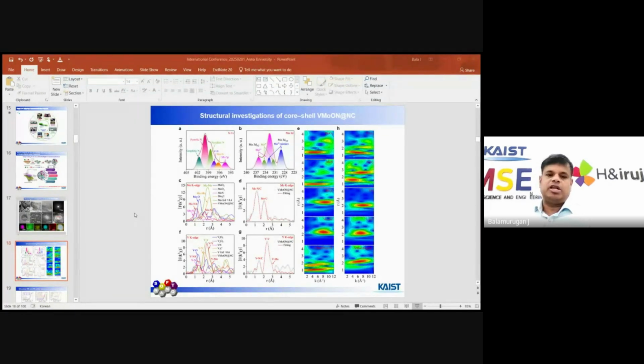I told you XAFS is one of the great tools to find the local structures. This is the comparison with oxide, nitride, and carbide-based materials and metal foils. When we look at the R value, below 2 we can see the metal bonded with non-metallic anions, like metal with oxygen, metal with nitrogen, or metal with carbon. In the region after an R value of 2, we can clearly see metal-metal bonding. From the studies, we can see this material contains metal-nitrogen bonding rather than metal-metal bonding. We also show the fitted diagrams. From the fitting curve, we can see three different types of nitrogen and one carbon, because the molybdenum is bonded with nitrogen as well as carbon, not only nitrogen.